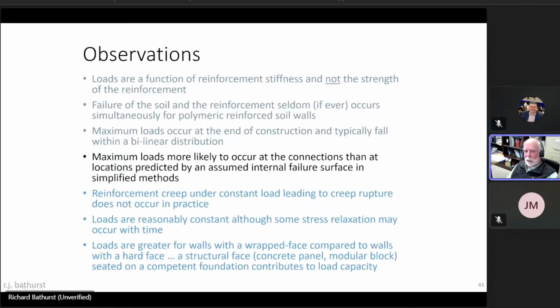Another important and practical observation was that we found that the maximum loads in the reinforcement are more likely to occur near the connections than at locations predicted by an assumed internal failure surface using simplified methods. I showed you that alignment between a Coulomb surface and the internal peak strains. But under operational conditions, this is not the case.